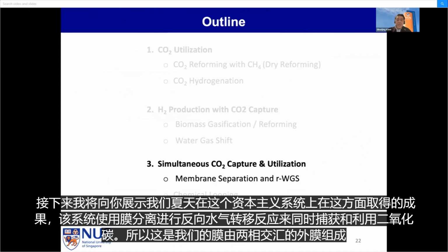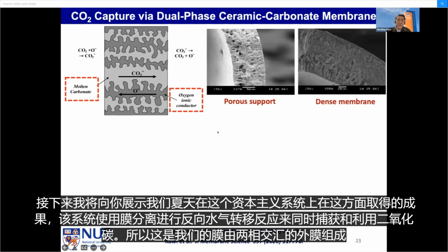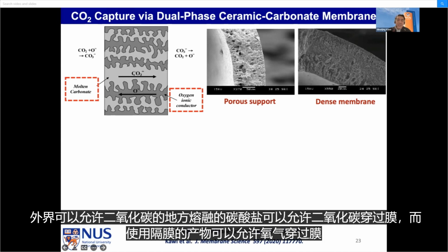Next, I will show you our summary results on the development of this catalyst system for simultaneous CO2 capture and utilization using membrane separation for reverse water gas shift reactions. So this is our membrane. It's made up of a dual phase mixed oxide membrane, where the molten carbonate can permeate the CO2 across the membrane, and the oxygen can be permeated across the perovskite membrane to the other side.